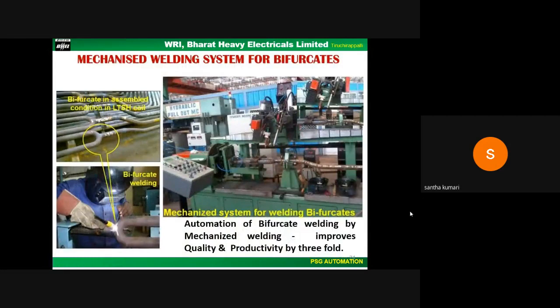Bifurcates are used in 500 megawatt boilers, wherein a U-tube, you can see here, and a third leg, a lengthier tube with bends, will be joined together at the bottom of the U-tube. This was earlier done by the manual GTAW process. The edge preparation on the U-tube will be made through a pull-out system, and making a defect-free weld was really challenging. By developing a mechanized system, the welds were made successfully with a GTAW root pass and filler passes with GMAW.